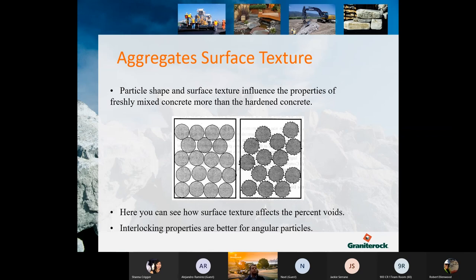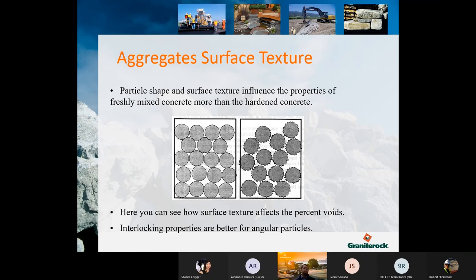Another component of aggregates that needs to be considered is the texture of the surface. So particle shape and surface texture influence the properties of freshly mixed concrete more than hardened concrete. And here you can see how surface texture affects the voids between them. Interlocking properties are better for angled particles. So considering a smooth rock versus a crushed rock, the mechanical properties of interlocking actually create more strength than a smooth rock would.